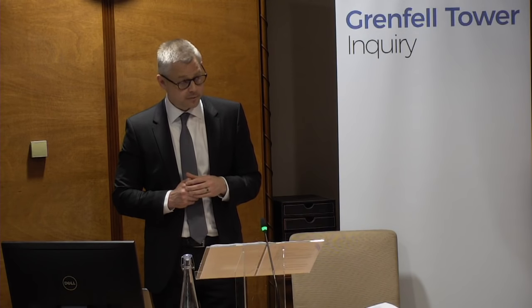The flame and pyrolysis products produced by the burning of the material rise due to buoyancy and heat the surface of the material, and this results in high rates of heat transfer to the surface of the material. As the unburnt material ahead of the burning region is heated, it begins to pyrolysize and generate flammable gas. As the gas ignites, the visible flame spreads rapidly. Typically, but not always, the rate at which the pyrolysis front advances is faster than the rate at which fuel is consumed. This is an important point.